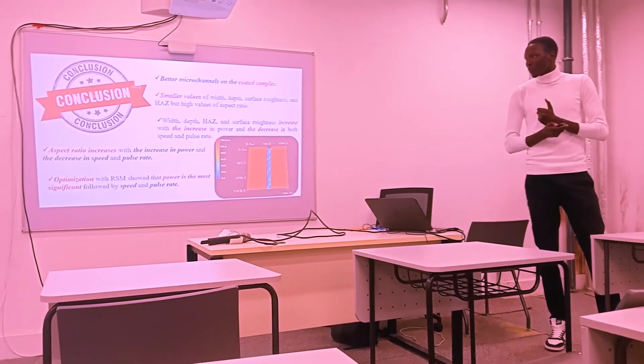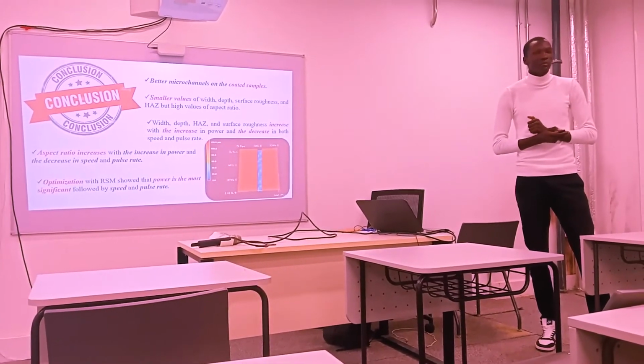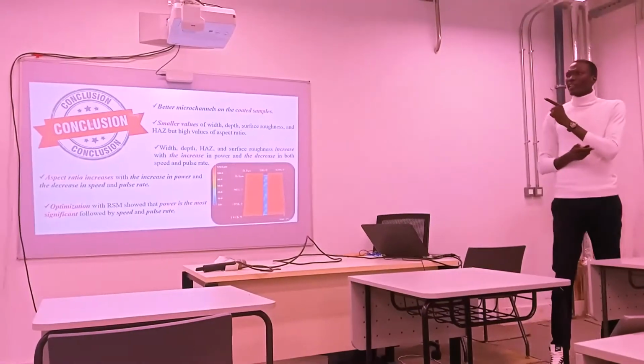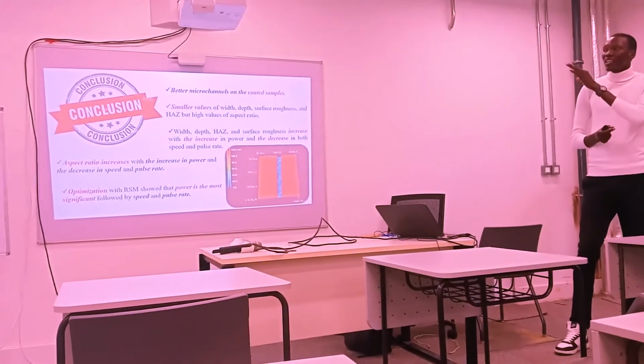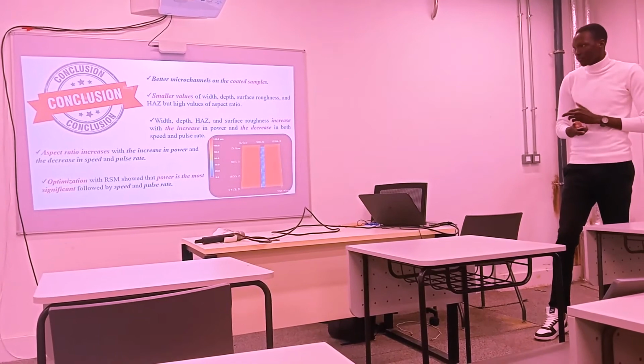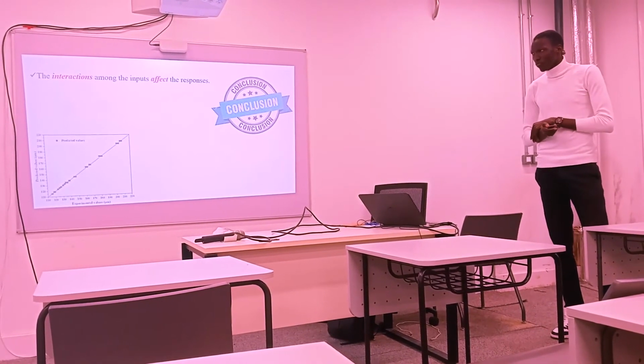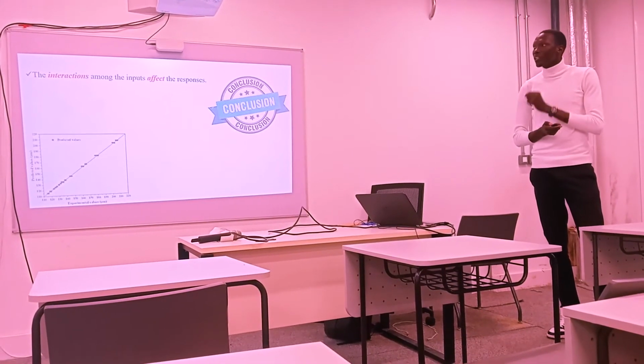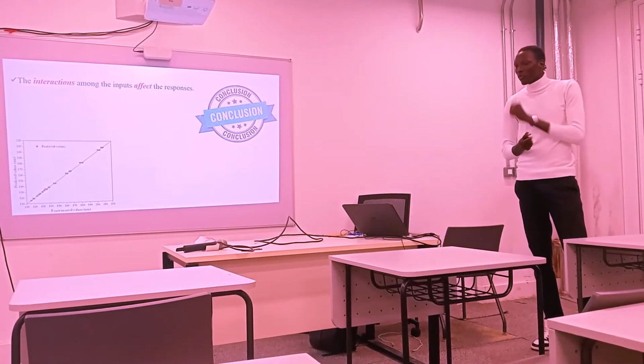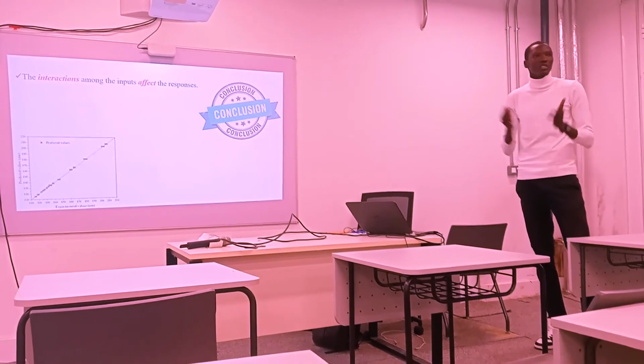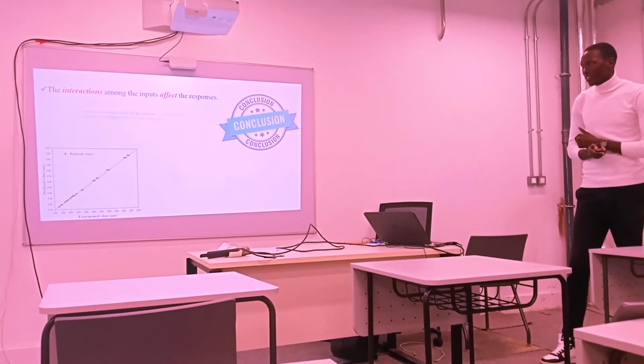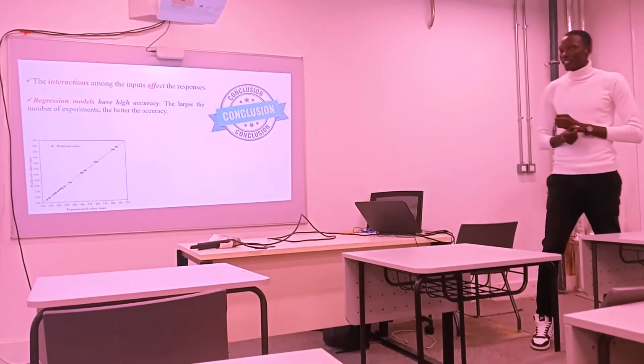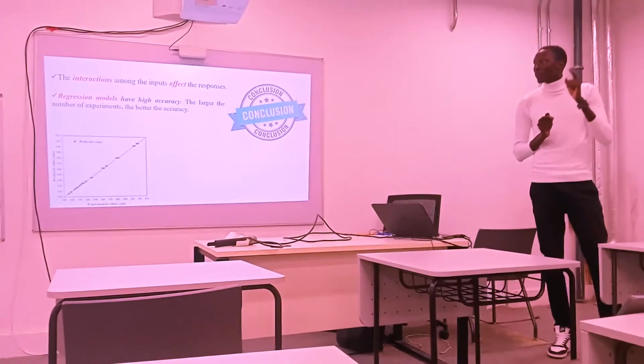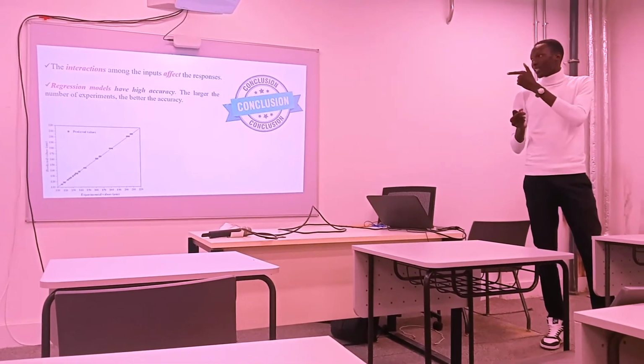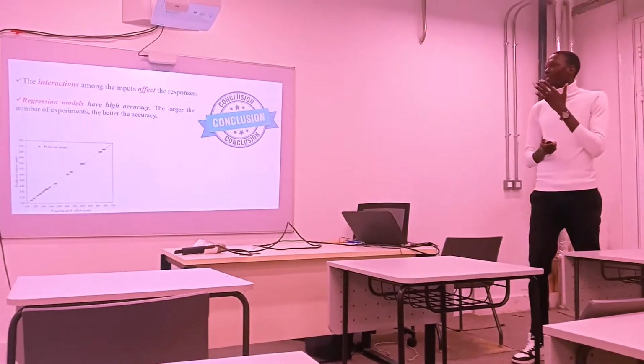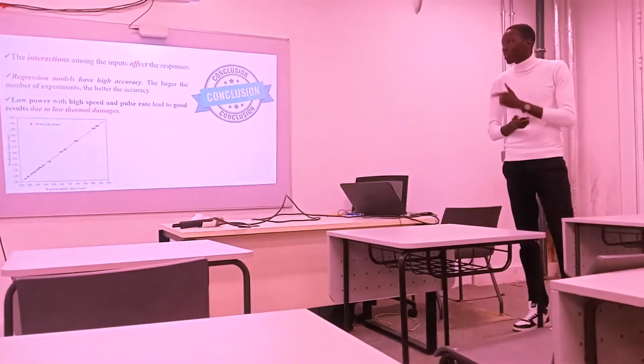Now, when we optimize with response surface methodology, we got that power is the most significant factor, followed by speed and pulse rate, which is in line with the study done by Mohammed and others, as we saw. They got the same one. And then, the interactions among the inputs affect the values of the response. For example, we saw in the interaction plots, power interacting with speed affects the values of all the responses. And then, the regression models have high accuracy. Those equations that we saw under response surface methodology, we saw that the models have high accuracy from the plots we saw, and the predicted values compared with the experimental values were so close.